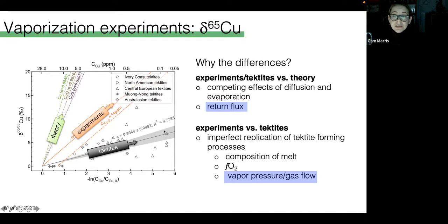So the theoretically derived alphas would be relevant for free evaporation in a vacuum, leading to the highest fractionation. And while we don't know the exact partial pressure of evaporated species at the surface of the melt in either our experiments or in the molten tektites, it would make sense that the vapor pressure in an impact plume would be higher than that induced by the gas flowing in the levitation furnace. And this matches the data here, where we see that our levitation experiments are more fractionated than tektites.